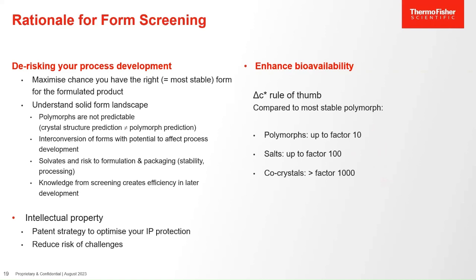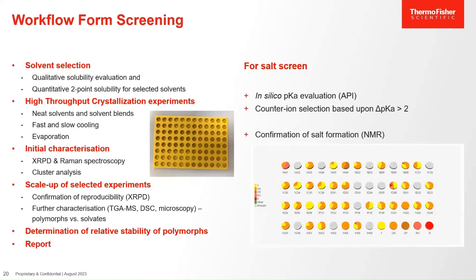So what is a typical workflow for a solid form screen? Initially, solvent selection, we're assuming we're starting from zero knowledge. We get a powder which we assume is a particular molecule. We characterize the molecule. We make sure that this molecule is what it's supposed to be. And then we start looking at solvents, either through a qualitative solubility evaluation or quantitative two-point solubility. Usually we use both approaches, that we scan a range of solvents and then focus on those that are most suitable for screening activities and get more quantitative data.